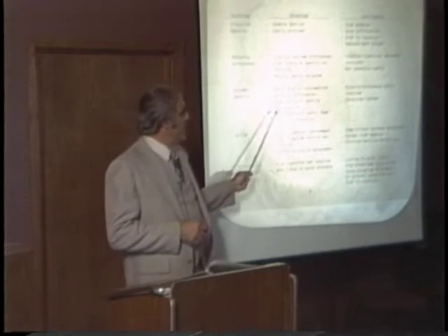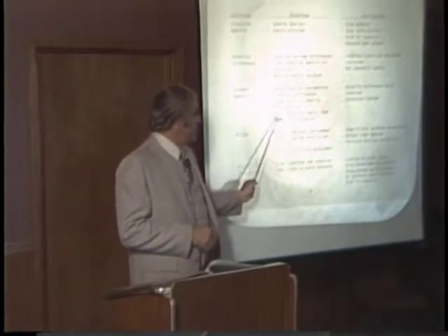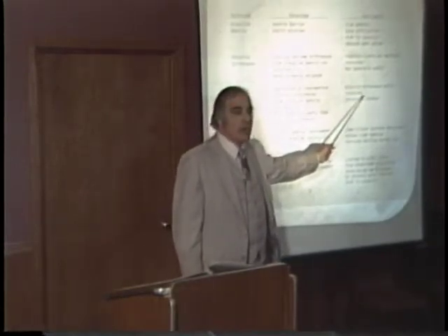Polymer density, it's applicable where you have intermediate polarity differences. We can slow things down simply by increasing the density of the polymer. You do not require a high cross-link density, which means you can control the modulus much better. And it's more generally useful than polarity differences. However, you still require a polarity difference somewhat. And the selection is limited because there are not a whole host of materials out there that would satisfy this kind of a requirement that we can use in this business.